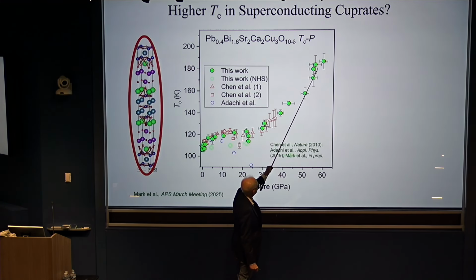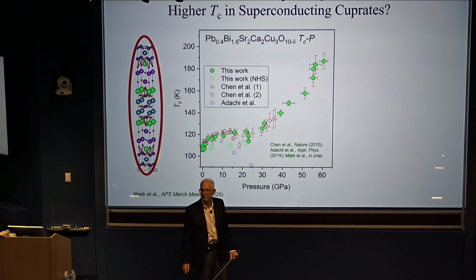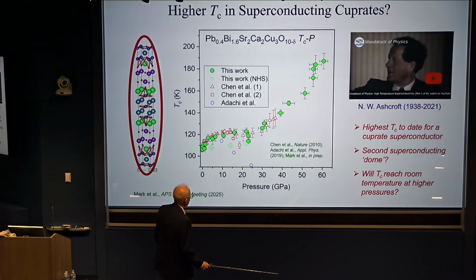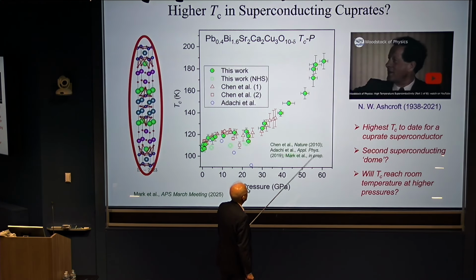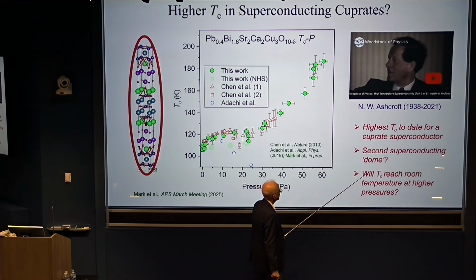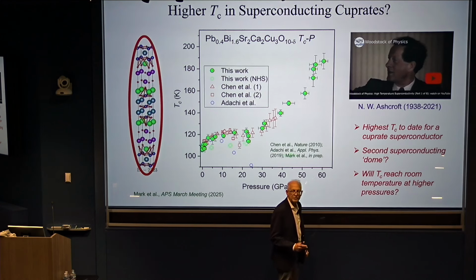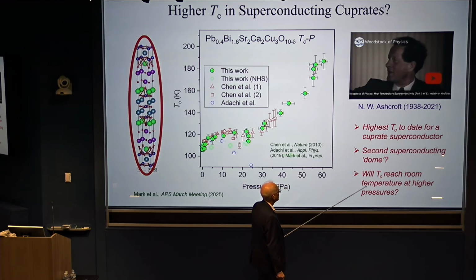The experiments are now here. He is actually doing measurements as we speak at Argonne to try to push this further, but this is already close to 200 Kelvin. So this is the highest TC measurement of a cuprate, which is quite exciting. And in fact, this idea that maybe you could get cuprates to room temperature was discussed at the Woodstock of Physics, which was presided over by Neil Ashcroft, and I believe he made that statement back at that meeting. I happened to be there. I was a postdoc at the time.